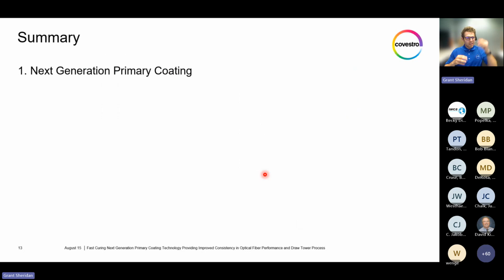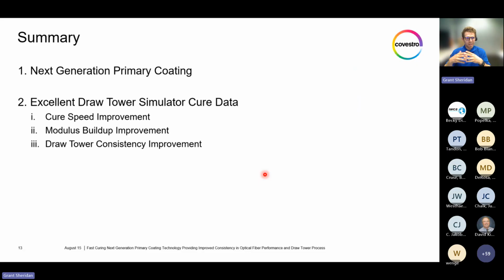So overall, it's been hopefully demonstrated that this next generation primary coating and primary coating technology improvements over the current technology. It demonstrates extreme cure speed improvements over the current technology, modulus buildup improvements, and draw tower consistency improvements to meet the switch to UV LED lamps, as well as draw speeds in excess of 3,000 meters per minute. We also enable better low temperature microbending performance, in addition to the significant improvements in cure speed.